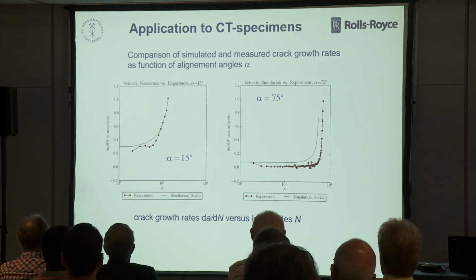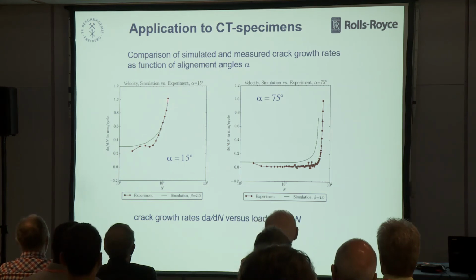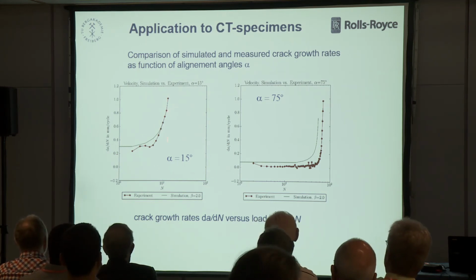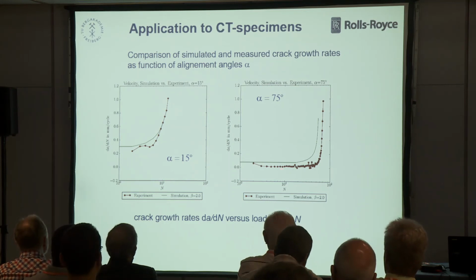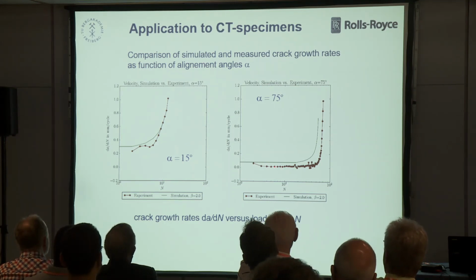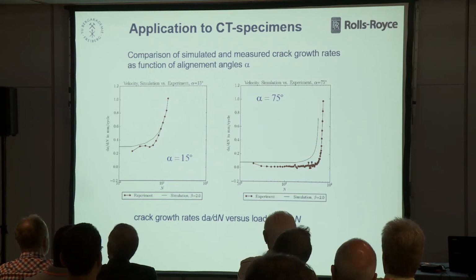For alpha 15, the crack very fast follows the new direction after about 20 cycles. For the hard declination, you see the crack needs many cycles to find the direction, but then it goes very fast.